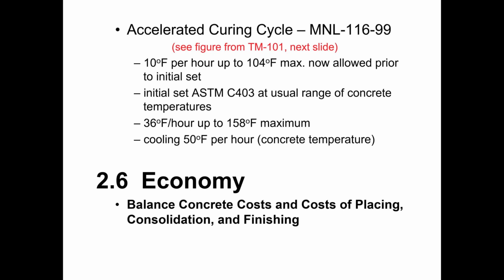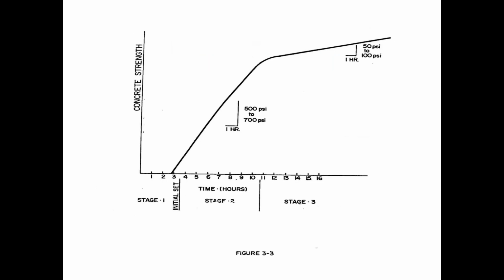If you look at this next slide, this shows the 3 stages of the initial curing of concrete. This is not in your book, but it is something that you've probably seen in level 1 and level 2. So stage 1 is that period from when the concrete is mixed until it reaches initial set. During stage 1, we have limited heat that we can apply to the form because we need to keep the temperature increase to less than 10 degrees Fahrenheit per hour up to a maximum of 104 degrees. Once we reach initial set, then we can jump up to 36 degrees per hour up to a maximum of 158. We refer to this as stage 2.